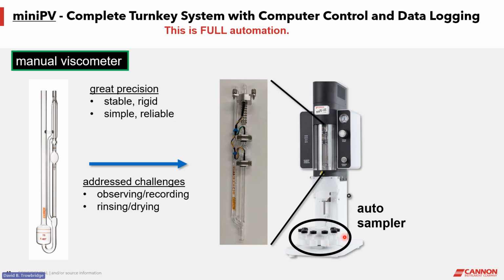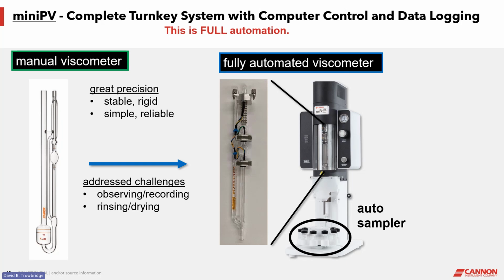This rack of samples will raise up and introduce vials one at a time into the tube tip, and the sample is drawn up into the tube by vacuum. And so the only material that is wetted is the glass in this section of the tube by the sample. Then when we want to wash it, as I said, solvent and drying air is introduced from the top to displace the sample and dry the tube. So all these features together give us the fully automated viscometer that has these features.